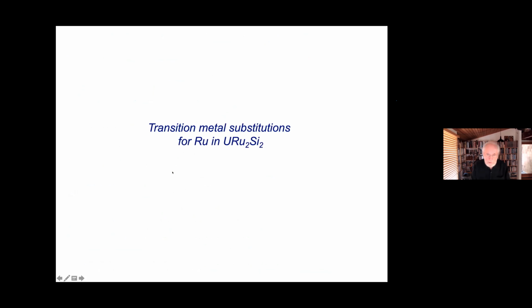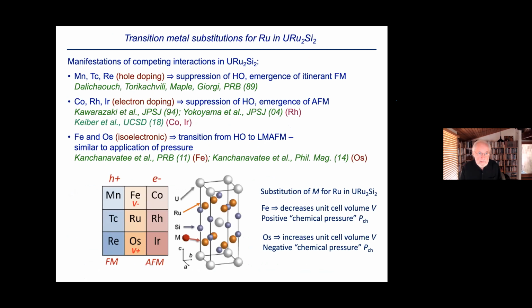Okay, so let me now turn to the transition metal substitutions for ruthenium in uranium ruthenium 2 silicon 2. So anyway, these are manifested in different ways or give rise to different phenomena. So this is just a little figure here. So on this side, if you make these substitutions, you dope the material with holes. These substitutions dope it with electrons. These are isoelectronic substitutions, but one important thing is that when you substitute iron, it decreases the unit cell as you add more and more iron, the volume of the unit cell, whereas osmium increases the volume of the unit cell. So that will turn out to be important.